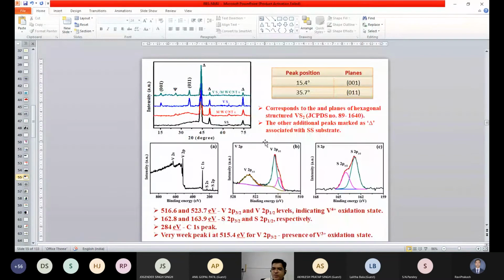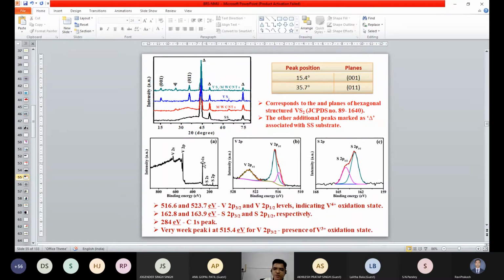So here this is the X-ray diffraction pattern and XPS, showing that the vanadium sulfide we got has a hexagonal crystal structure. In order to see the oxidation state, we have done XPS analysis to confirm the oxidation states of vanadium and sulfur. Vanadium is present in the V4+ state as well as the 3+ state, so that it can have a better specific capacitance.